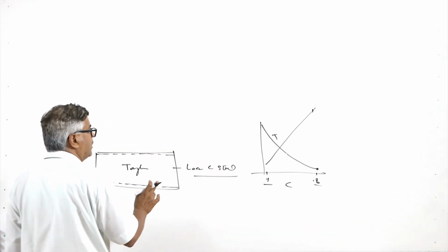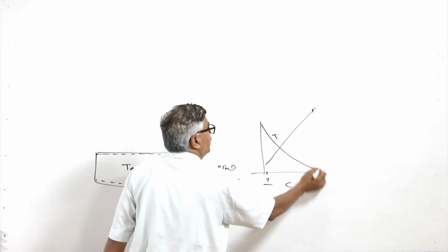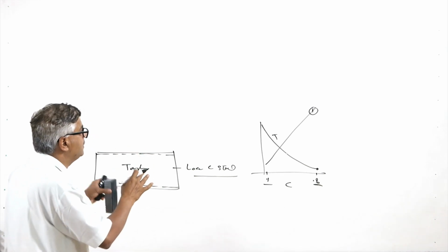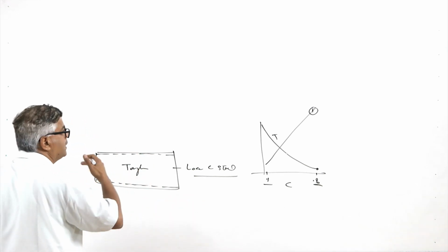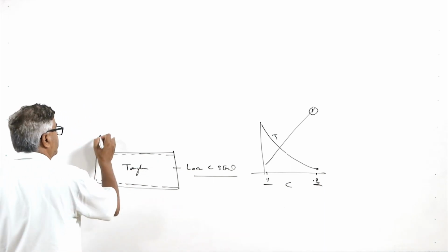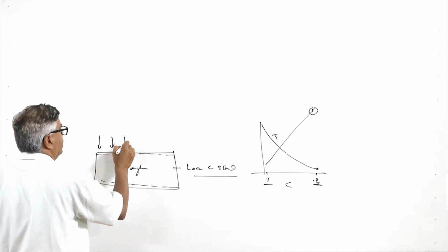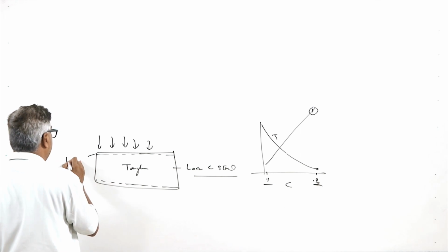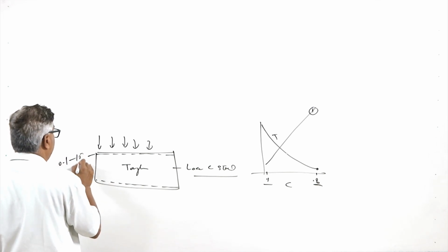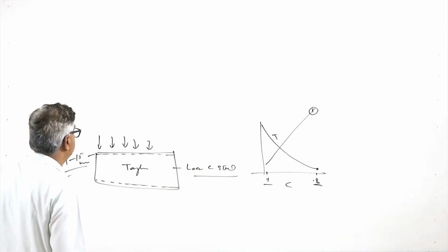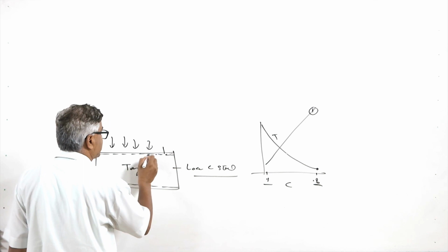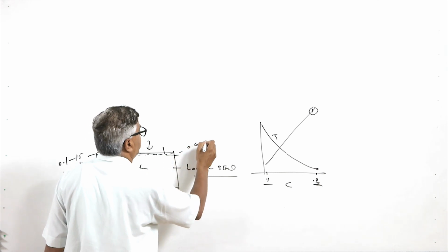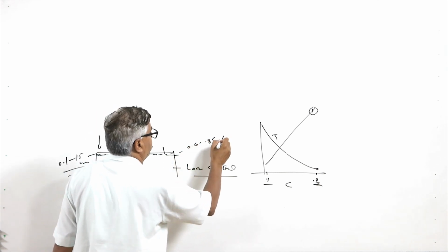So what combination we want, that surfaces are hard corresponding to the 0.8 level of the carbon content while the core remains still tough. So for this purpose only the core composition is maintained while the surface composition is enriched with the carbon. So the carbon is introduced near the surface layers, and this can be introduced up to the depth of say 0.1 to 1.5 mm depending upon the purpose for which it is to be introduced. So once the carbon gets enriched near the surface layers, this enrichment is done up to the point like say 0.6 to 0.8 weight percentage.